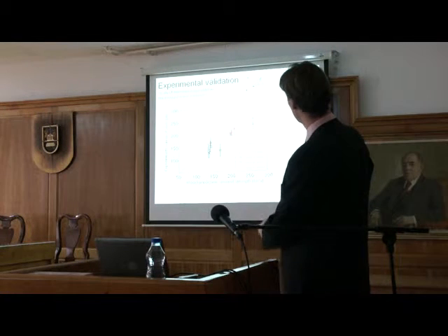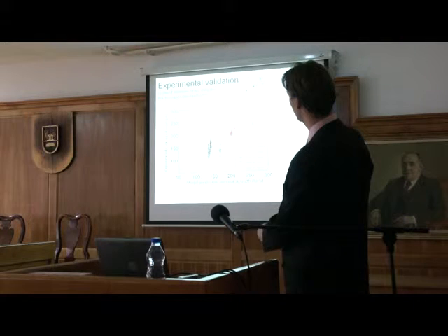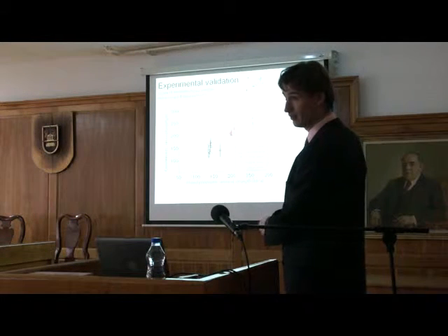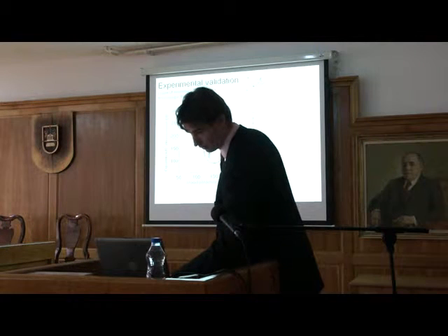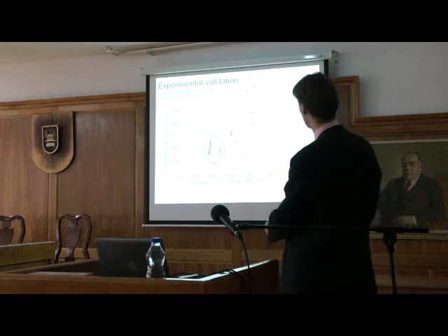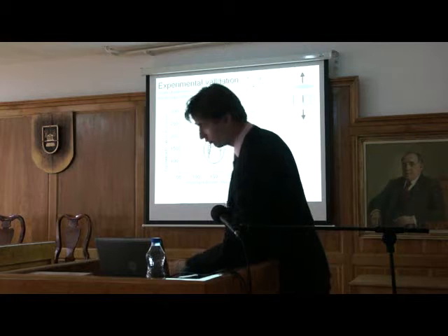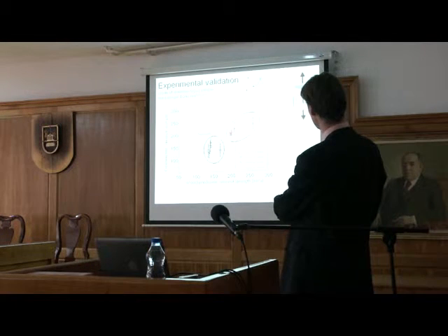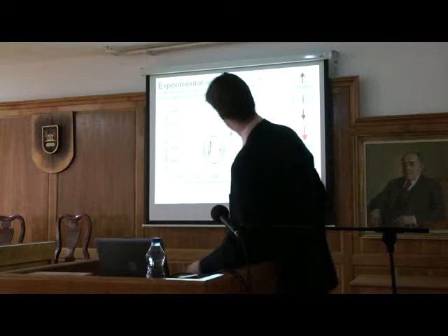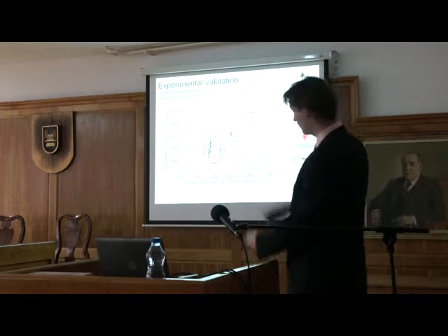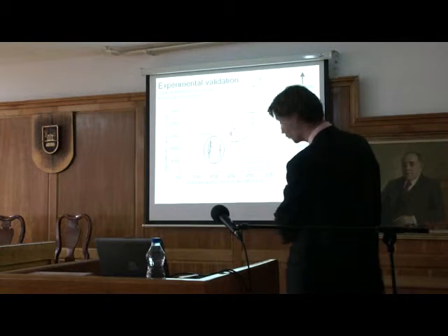So now, and this is one of the validations again. Uniaxial strength for different tissues works very well. This is now the independent strength checking. In tension, it's less than in compression. That's very logical, right? In tension, this needle would fail, this kind of crystals, right? And in compression, you have to press much longer until this needle would fail in tension.